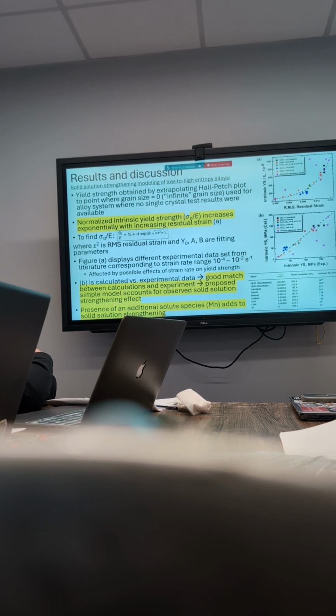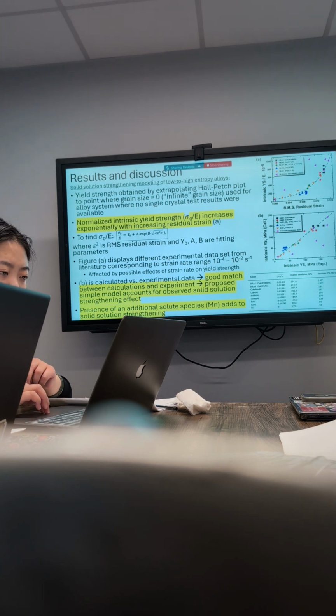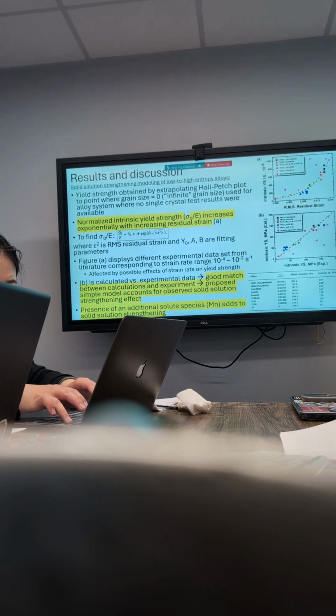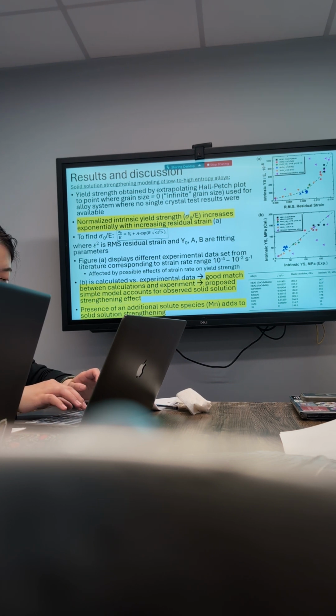So now we're going into the solid solution strengthening model that they said they were trying to create. They found the yield strength obtained by extrapolating the Hall-Petch plot to a point of 0 was used for alloy systems that didn't have a lot of data available. The normalized intrinsic yield strength, which was their sigma naught divided by Young's modulus, increases exponentially with increasing residual strain. To find that sigma naught, they use this equation. The figure at the top displays the different experimental data sets from literature that correspond to their strain range of 10 to the negative 4 to 10 to the negative 2 that they used.